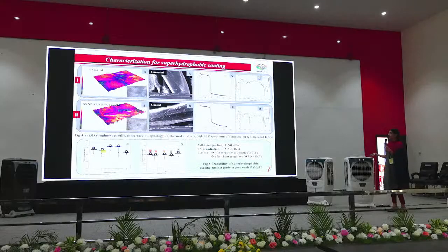And the FESEM result substantiates this, that is, micro-nano roughness structures were seen on the coated surfaces, and the coatings were also found to be uniform, compact, and there is no closure of the crisscross junctures. Therefore, we found the coatings to be breathable and lightweight. The TGA-DTA curves showed an additional weight loss between 400 to 800 degree, which is attributed to the mass loss from the decomposition of the coatings. And the additional peaks in FTIR compared to the uncoated ones show the successful incorporation of the polymer composite coating.